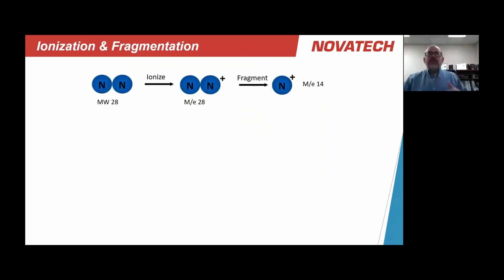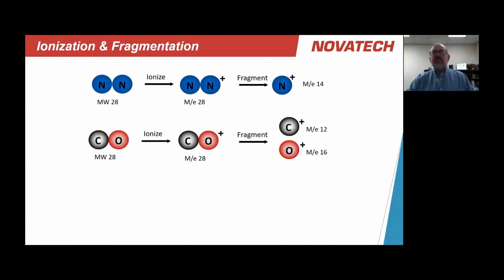What does that all mean? As we look at the different molecules, and I'm not showing hydrogen here for this example, we see that the molecular weight of the molecule is potentially problematic because nitrogen has the same molecular weight as carbon monoxide. And so if I were to rely on only looking at mass to charge ratio 28, I wouldn't know whether or not I'm looking at nitrogen or carbon monoxide or both.